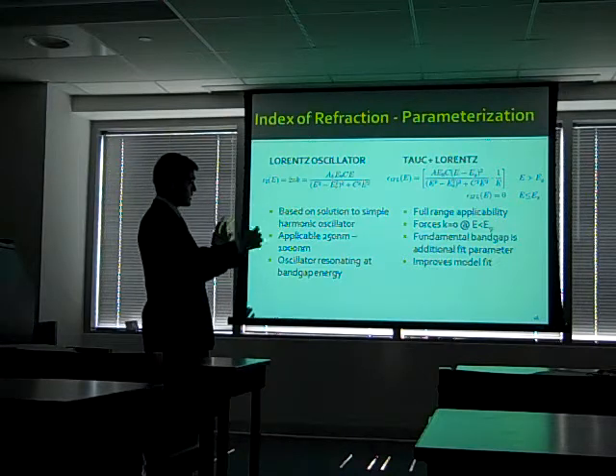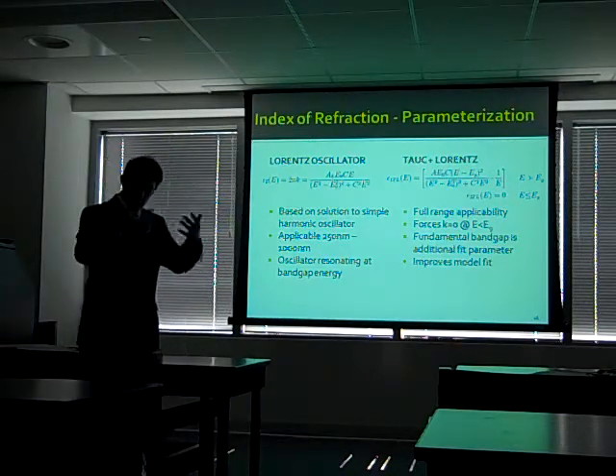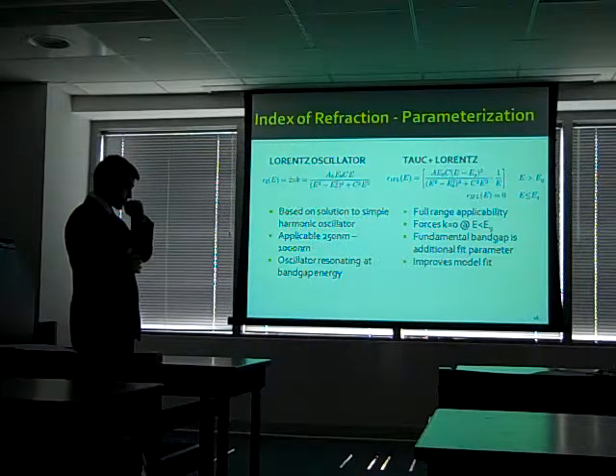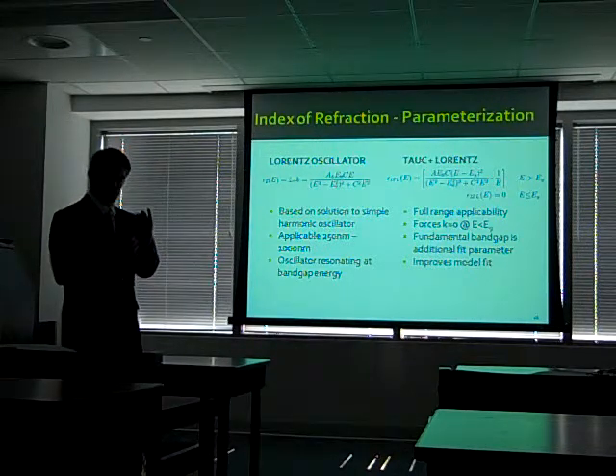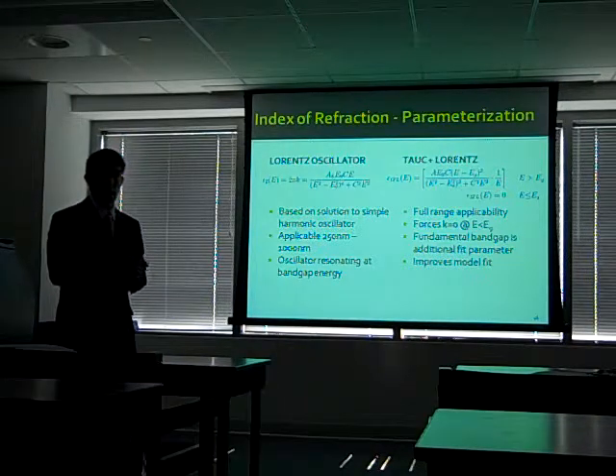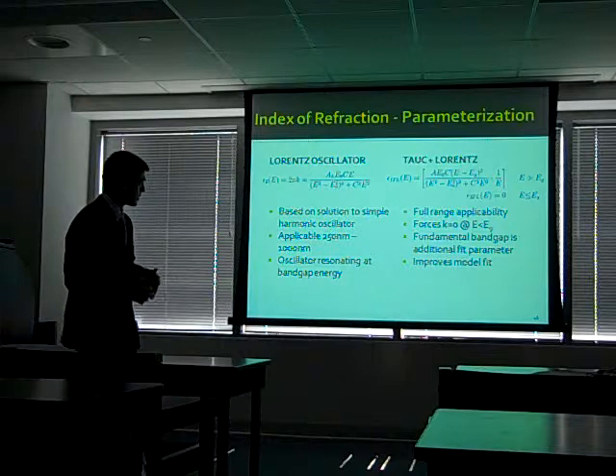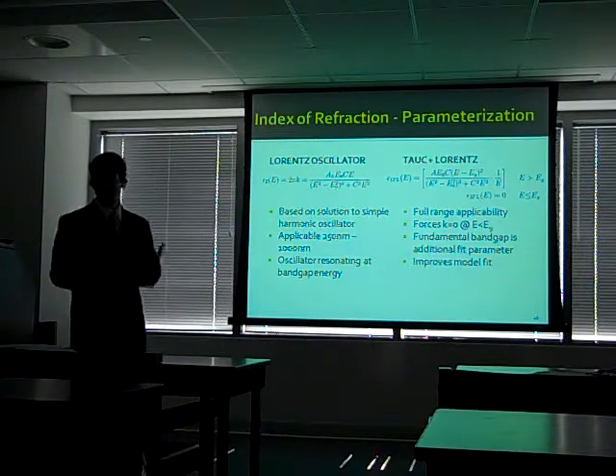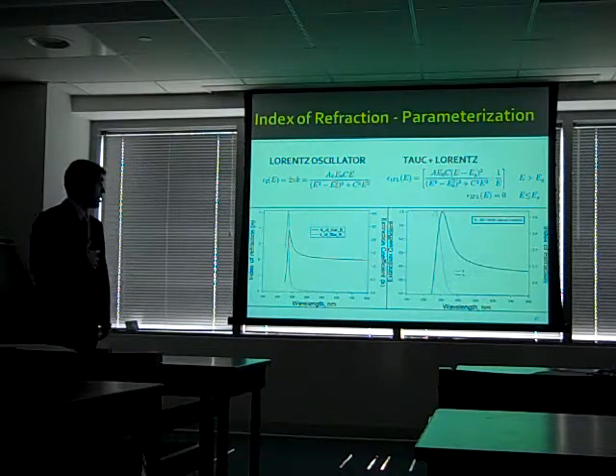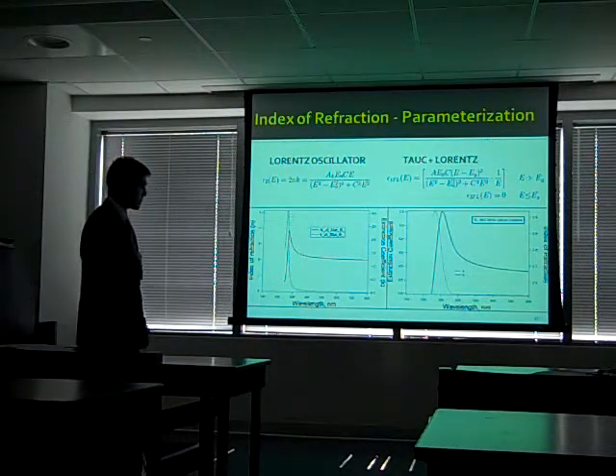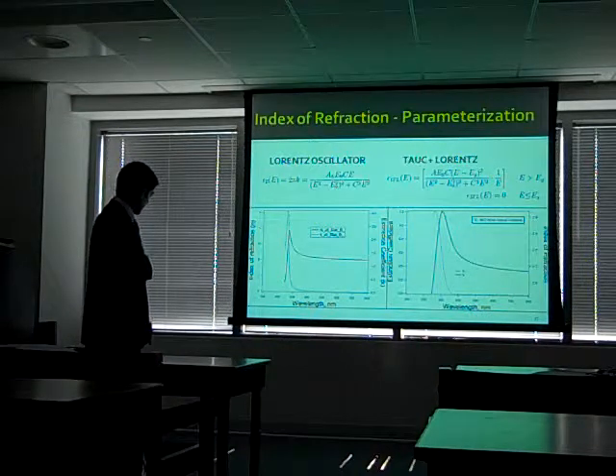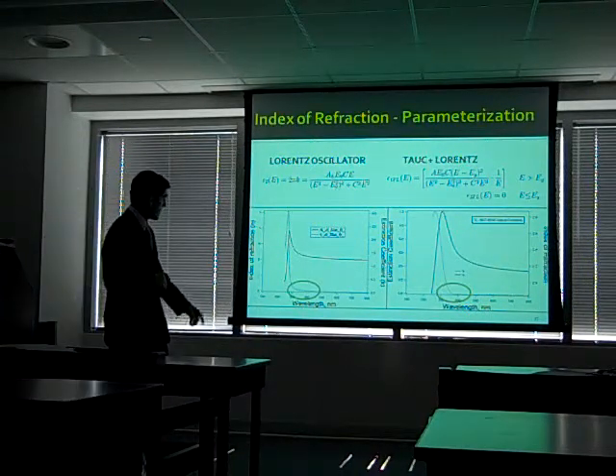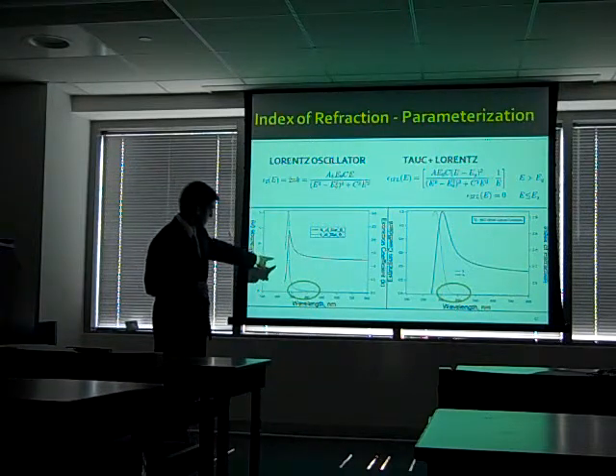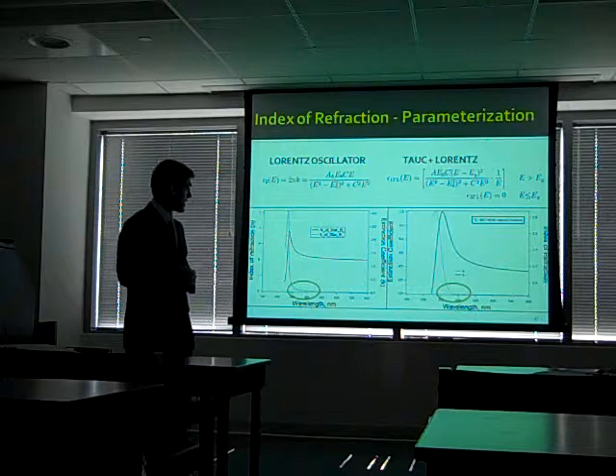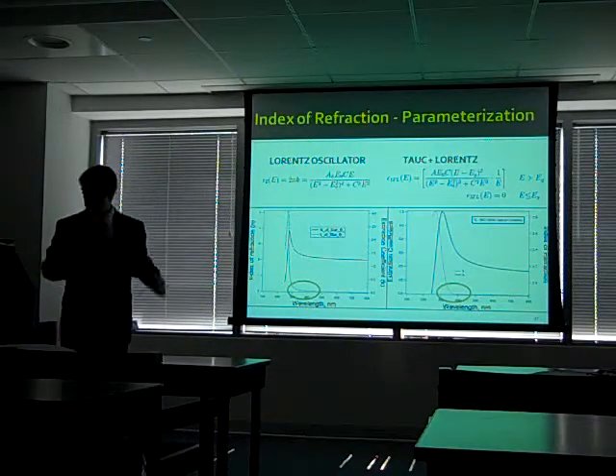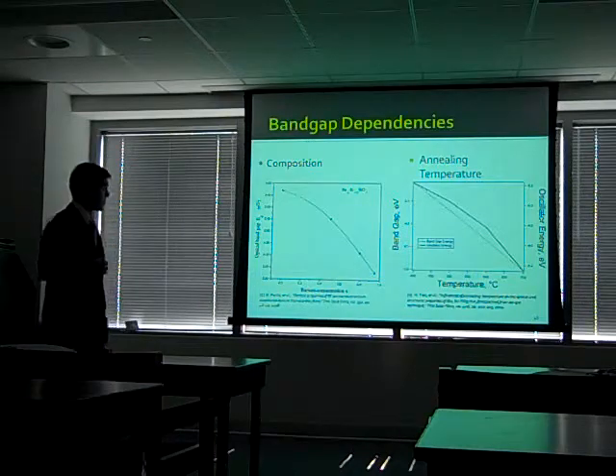The Tauc Lorentz model is built off of the Lorentz oscillator model, and it's better. It's a piecewise function which forces the extinction coefficient to be 0 at energies below the band gap. And so the result in using the Tauc Lorentz is an improved model fit. So that's the one that we use for the model. This is a representation of the parametrization. This is what it looks like. The main difference that I want to point out is how quickly the Lorentz goes to 0. The dotted line is the extinction coefficient versus the Tauc Lorentz. And then again, the result is a better fit in the model.